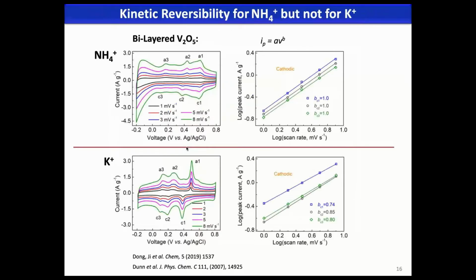So this is something we studied. We used the same bilayered V2O5 structure as the electrode, and we tried to insert ammonium ions and potassium ions into the structure, and look at a CV. The CV is completely different, especially this A1C1 pair, which is going to correspond to probably the same redox behavior of V2O5, but this A1C1 is vertically aligned, and according to the book by Dr. Bard, we call that kinetic reversibility.